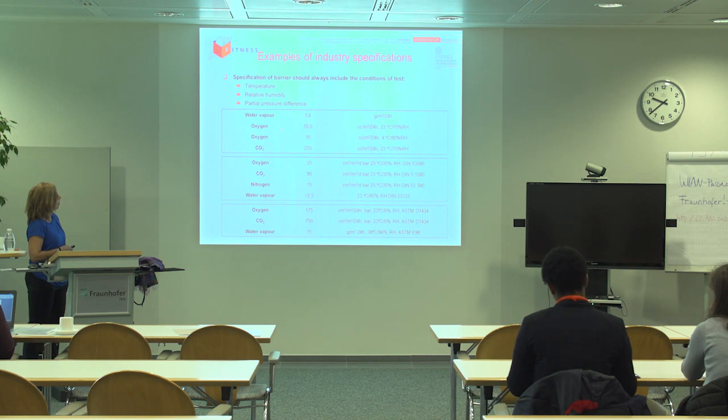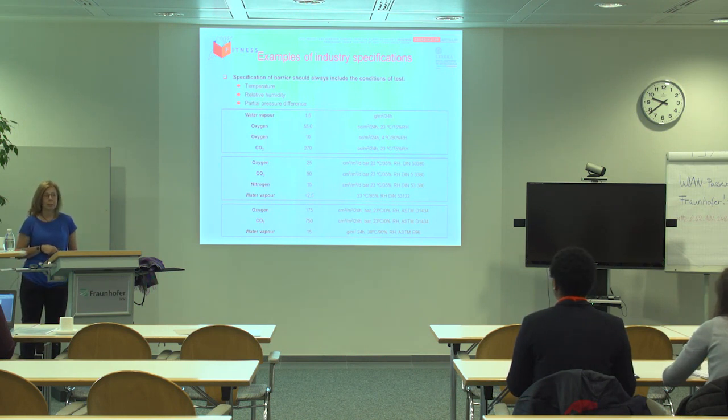Here for the oxygen, okay, they say the temperature, they say the relative humidity, yeah, but what is missing here? The pressure difference, the partial pressure difference of oxygen used in each, so the driving force, okay?